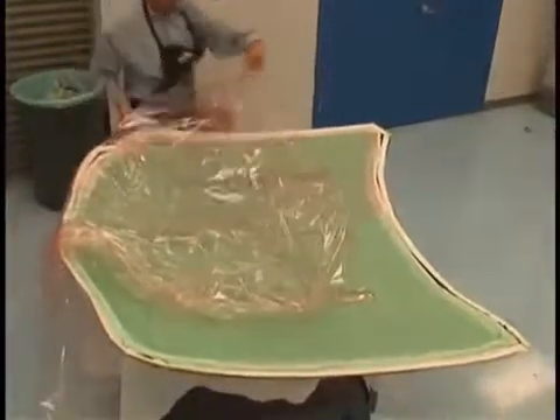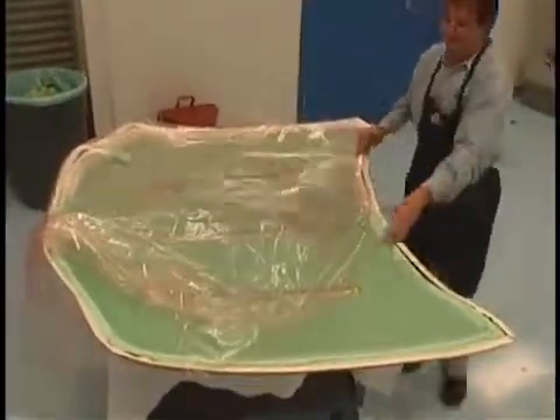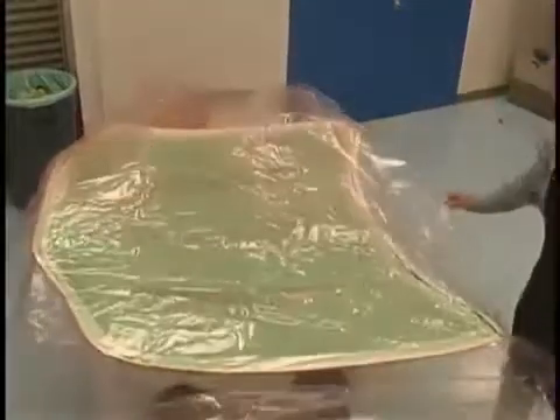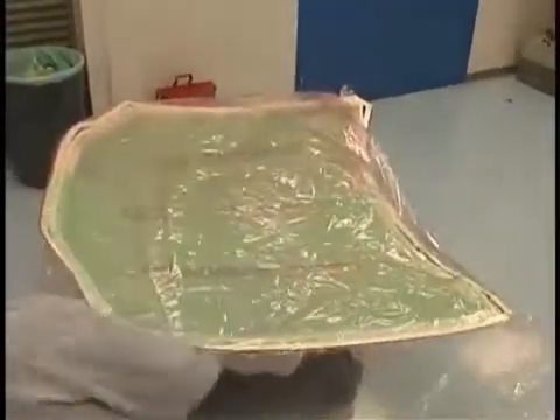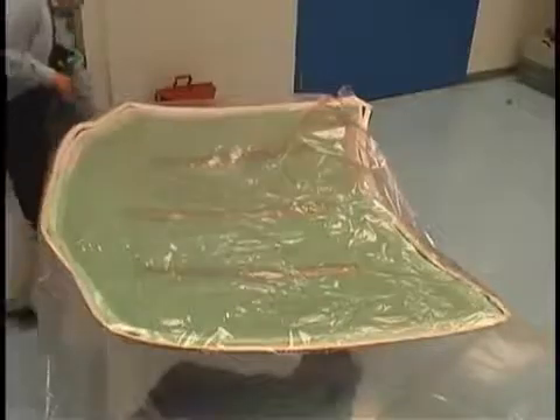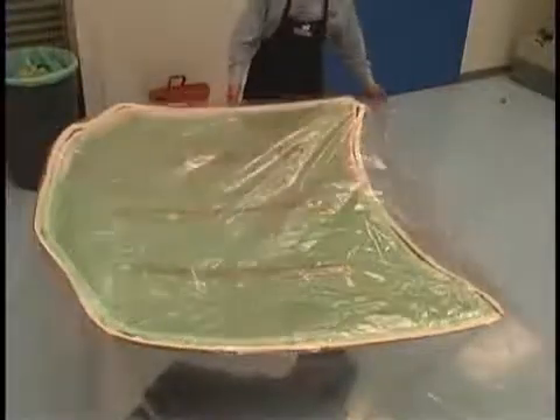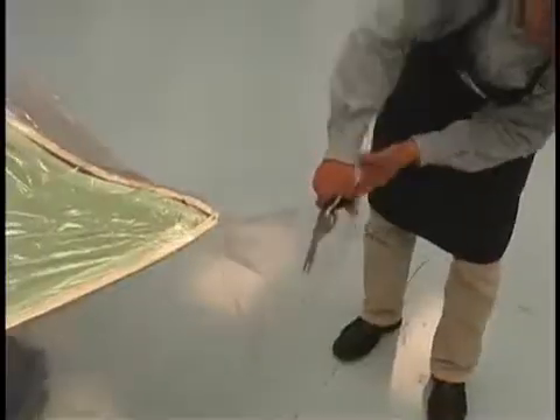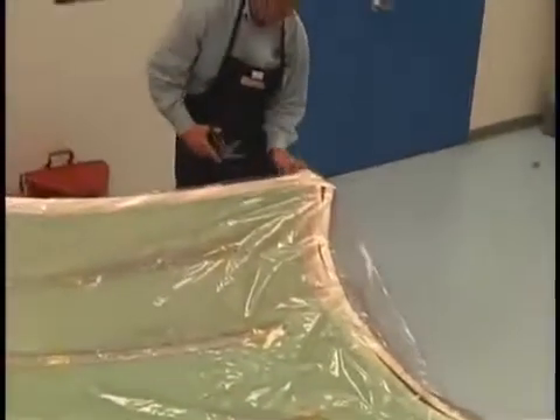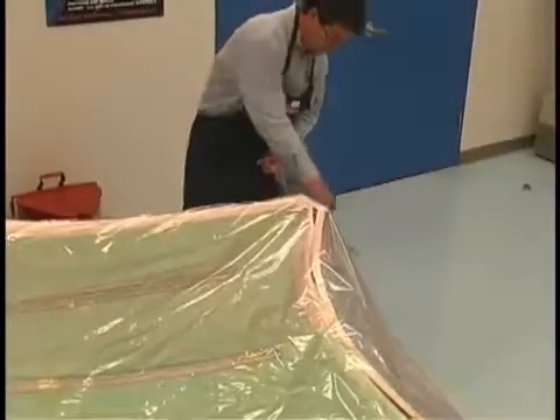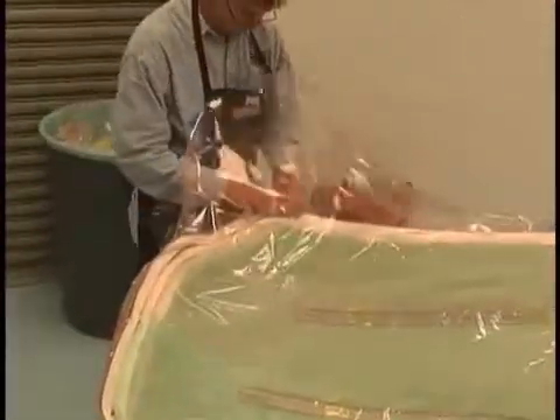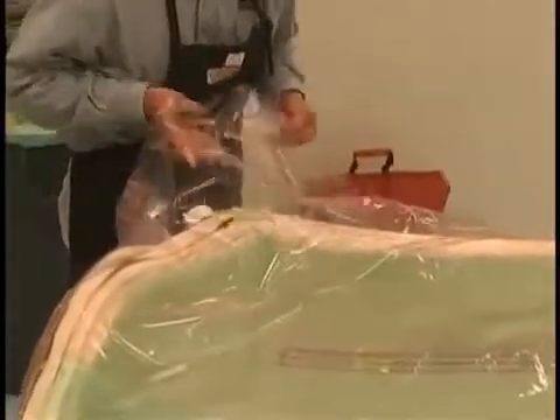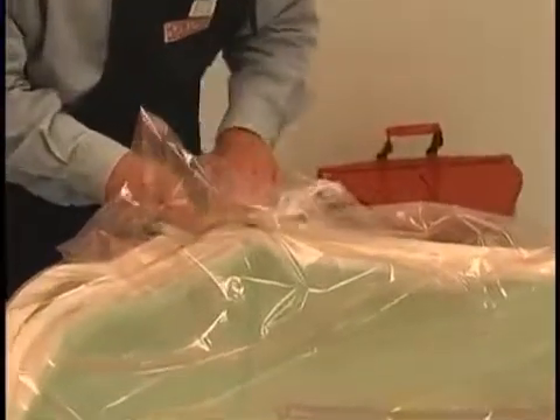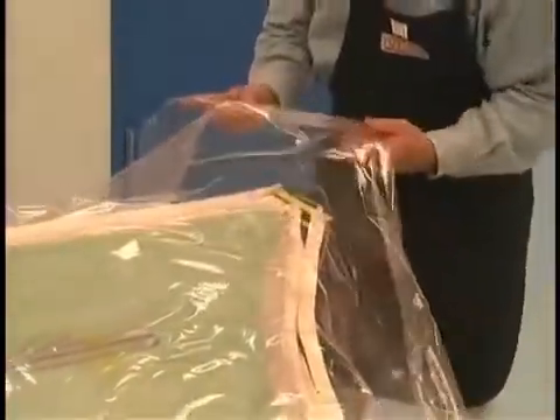Typically, the bag should be 30 to 40% larger than the part surface, depending on the complexity of the shape. Here we are using Airtech's Ipplon KM1300 vacuum bagging film. The vacuum bag is adhered to the sealant tape in strategic locations for proper positioning. The sealant tape paper is pulled away as the film is pressed in contact with the tape.